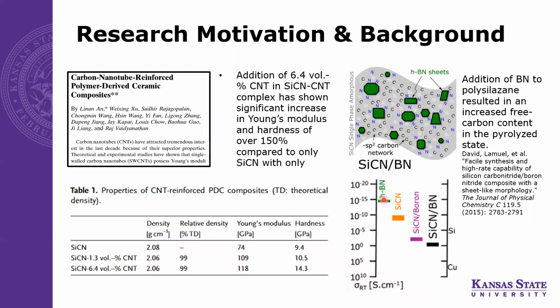In a similar study, multi-walled carbon nanotube was used as a reinforcement agent with a polymer-derived ceramic precursor, specifically SiCN, to yield a composite material upon pressure-assisted pyrolysis technique. A small amount of MWCNT actually improved certain mechanical properties such as Young's modulus, hardness, and damage resistance.